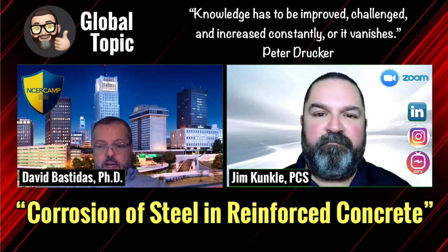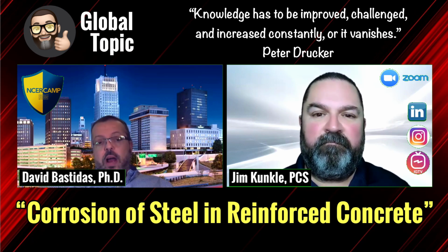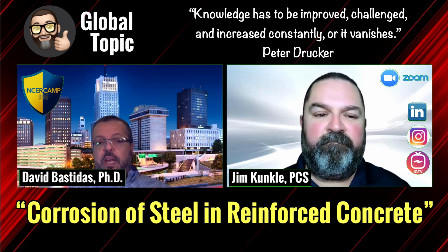So when those oxyhydroxides start to grow on the interface, on the surface of the rebar, no longer do we have this adhesion. In addition to this problem, what we lose is strength. So we are producing delamination, further spalling, and leading to cracks. When we get the crack, no longer do we have any integrity in our structure. And that will produce further ingress of external agents that will also increase the kinetics of the corrosion process. So we need to preserve the integrity of the rebar.